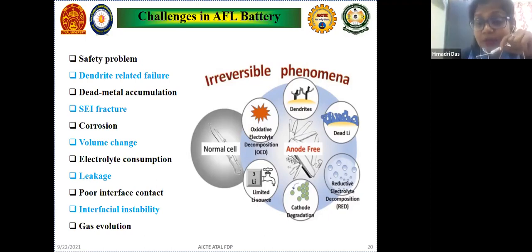Apart from that, there is a very limited source of lithium, as we are not using any anode. So the lithium source is only the cathode. It is a big challenge how the lithium source should be maintained well in the system, as well as the oxidation of the electrolyte and the cathode degradation, because now the total pressure is on the cathode. Cathode degradation happens, and the side reactions are similar to lithium ion batteries. So our challenges have increased in this anode free battery.